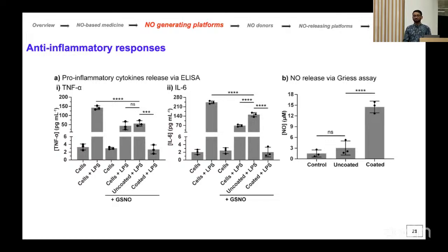GSNO, that's the source of nitric oxide, and we use the coated device, the coated catheter, we can see that there is the same level of TNF alpha as compared to the unstimulated macrophages. Because macrophages also produce massive nitric oxide, we also use a nitric oxide inhibitor to show that these effects are genuinely arising from our formulations, not from the cells.